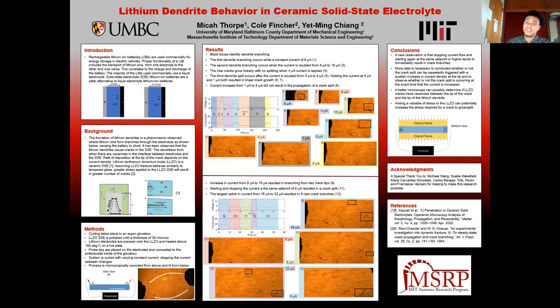In addition to those advances in our methods, our next big question is whether or not the application of external pressure, as seen in this figure in the conclusions, with clamping and applying pressure externally to a thin, rectangular electrolyte sample, will affect the propagation of the lithium dendrites if we do the same experiment with external force. Our hypothesis is that it will, since the ceramic electrolyte behaves mechanically, and the greater external stress is applied, the greater stress required to propagate cracks. So hopefully that's a result we'll see, because then this will provide a solution to this dendrite formation and a possible way to limit its effects of failing a battery.